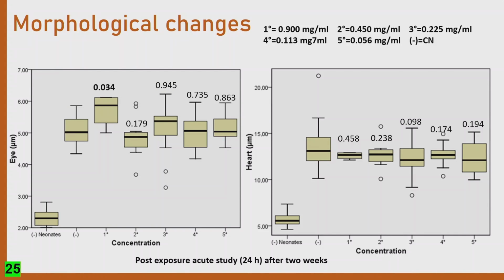Thank you. Nice talk, Juan. I just wonder if you have done any type of speciation study with the metals that are being removed, meaning the chemical form in which they are, which may be important. Yes, we have performed iron leaching studies, because we can adsorb the nanoparticles, but some iron can be leached into water. We have to be really worried about it, but it can be controlled with magnetic decantation. Magnetic separation can be really good when we are working with iron nanoparticles to avoid leaching.